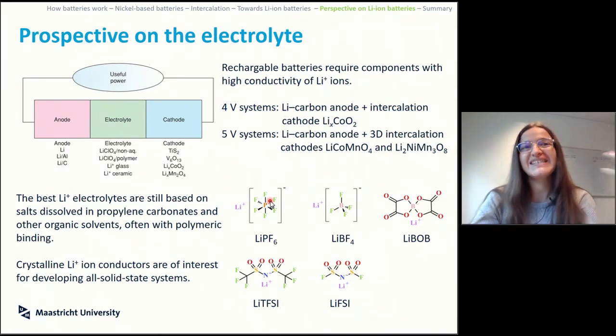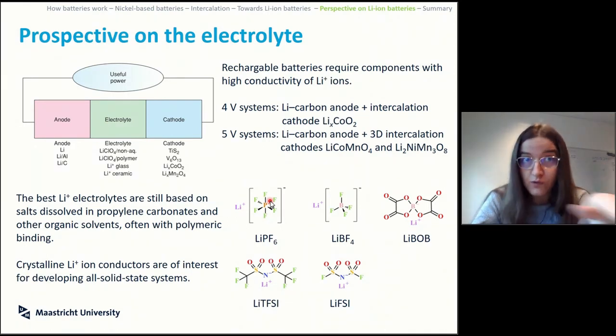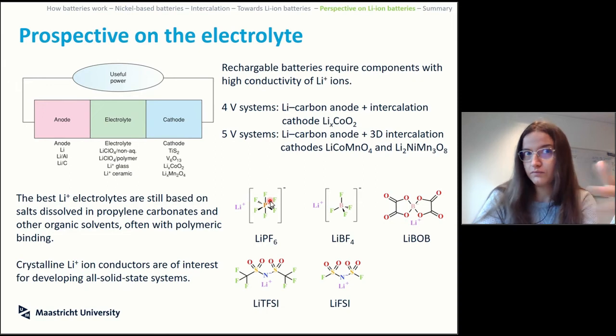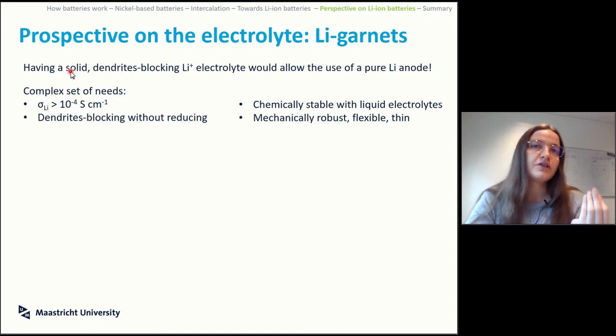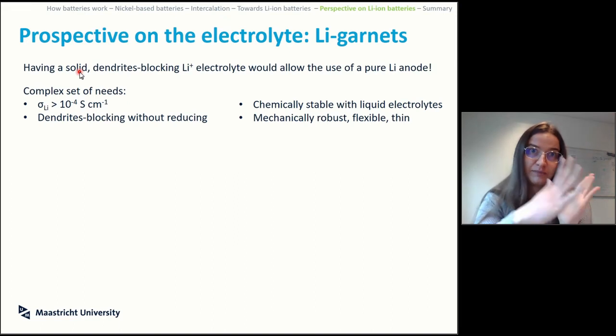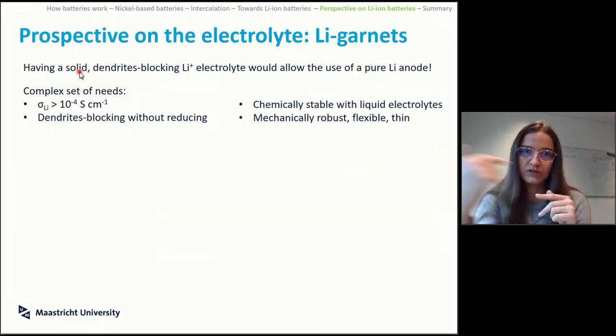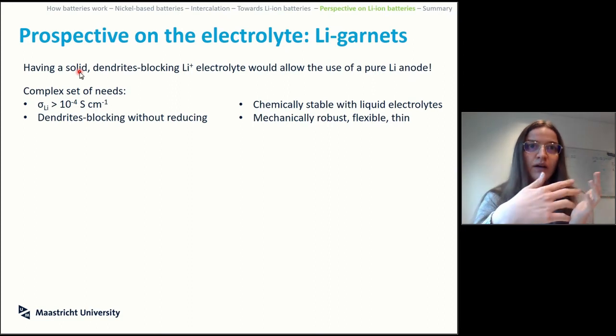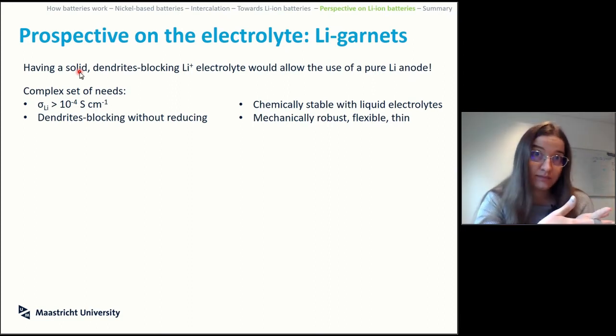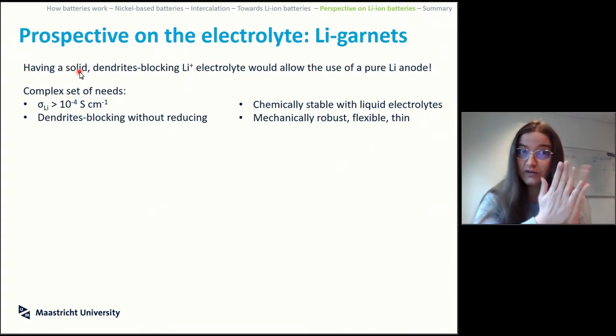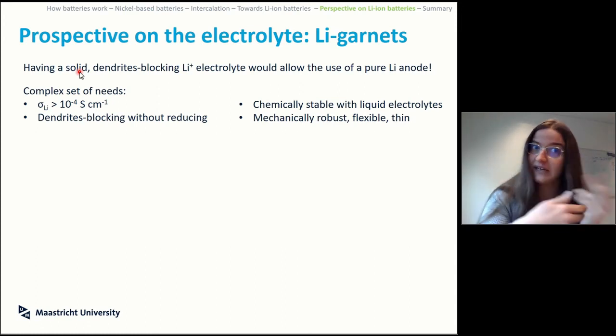If we could have a perfectly crystalline, so another solid, as the conductor of lithium that separates anode and cathode, you will have a fully solid state battery. Super interesting. What is potentially the problem? So having a solid will block the dendrite thing, because the solid will give a very precise point of contact and point of in and out with the lithium. So lithium could potentially be a solid by itself, right? So you could use fully metallic lithium, because if you don't grow anything and it goes smoothly in and out, then it's fine.